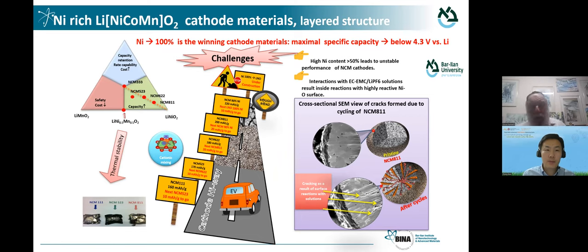We have phase transitions, we have stress, especially when we go to high voltage, approaching 4.3 volt, and stress means cracks. And if we have cracks which propagate to the surface, now solution percolates into the particles and destroys the particles, because the active mass here is reactive with the electrolyte solution. Remember, our electrolyte solutions for lithium ion batteries always comprise alkyl carbonate solvents, which are electrophilic.